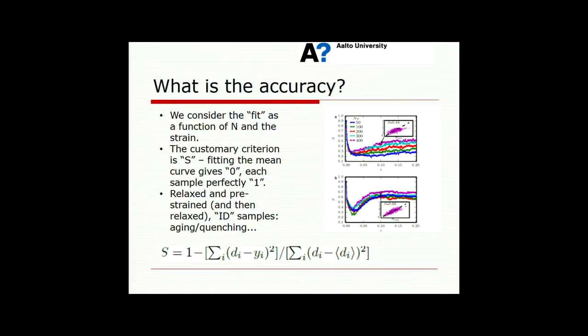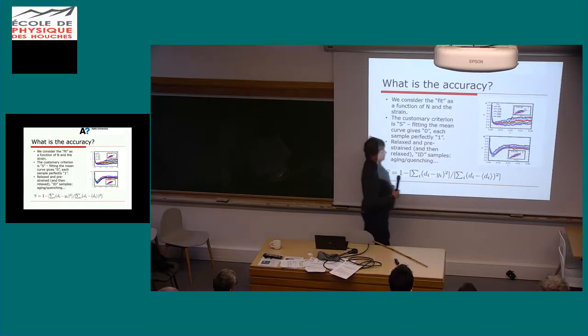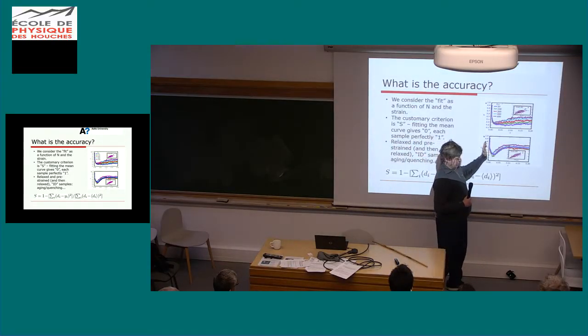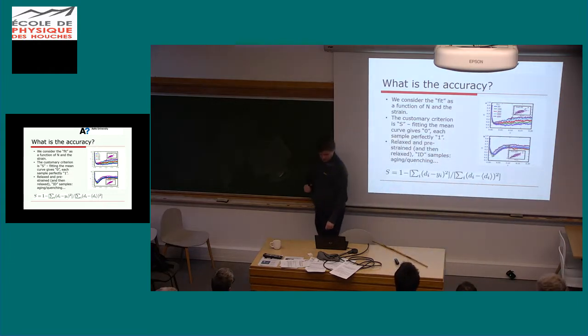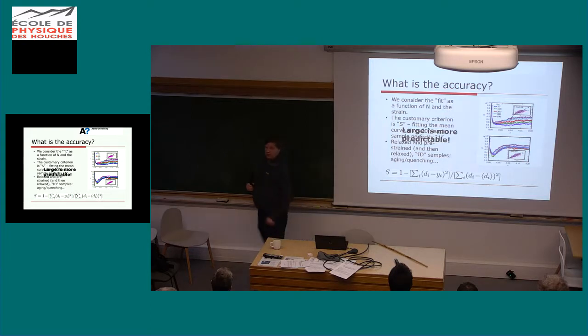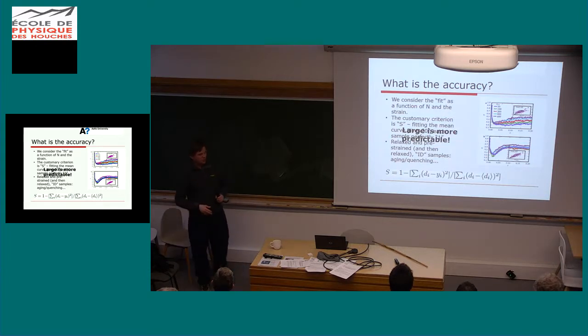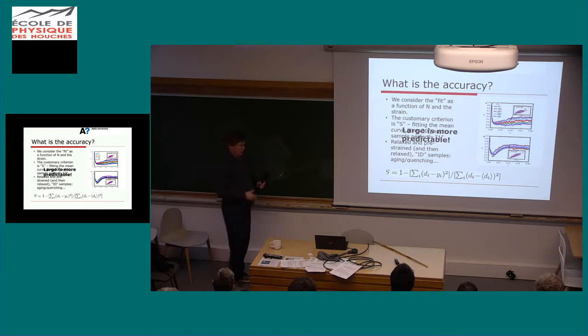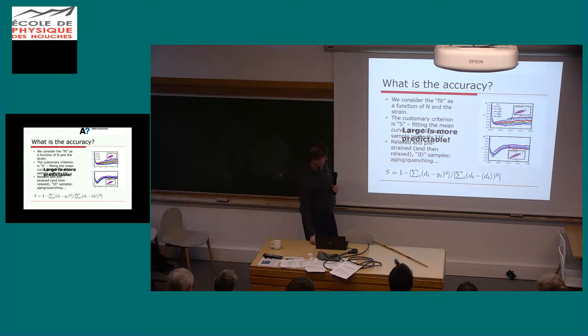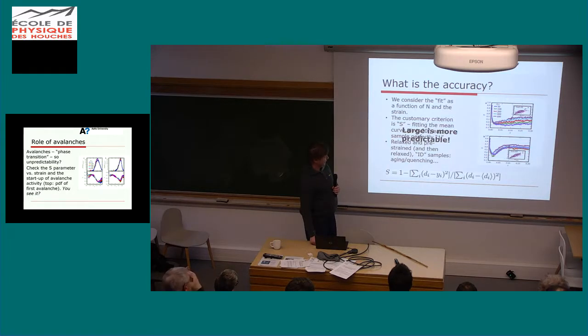Why is this so? Of course, it means that the systems have a memory. The main point of this memory is that, apart from some uncertainties because it's difficult to guess when the avalanche activity actually starts, there are large-scale features in this memory that become even more noticeable if you go to larger and larger system sizes. Larger is more predictable, which is kind of funny, but not a big surprise, because the question has always been why avalanche activity in plasticity is so difficult to see in real materials. There are various arguments about that, but it boils down to one way of putting it: the fractal dimension of the avalanches is always smaller than the space dimension of the system, so the relative weight gets smaller and smaller at larger and larger scales.